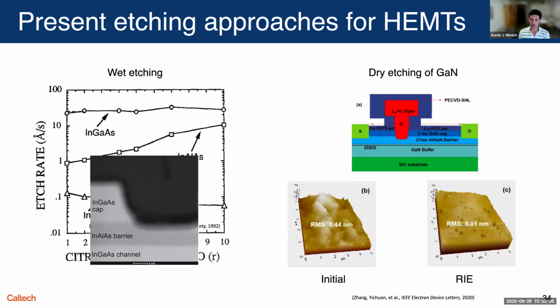There are other options, for instance, dry etching based on plasma. This is of interest presently for gallium nitride devices. The trouble is that they tend to increase roughness, and they also can be damaging for the semiconductor in terms of trap density. So you can see at the bottom on the right, the initial RMS roughness is 0.44 nanometers. After RIE, it's 0.81, which is probably indicating more traps.